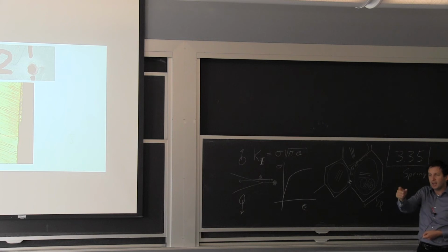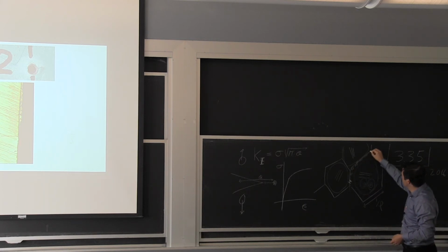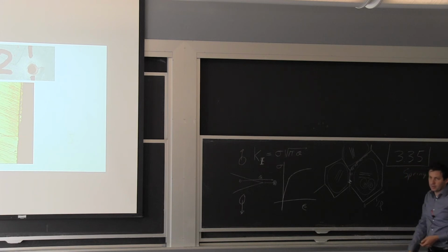and then all of a sudden you can have that very low fracture toughness because you'll just unzip through the grain boundaries. And I have plenty of images of that. It's something that's nice because you see the grains. If you want to know your grain size, you can just expose the high-strength steel to hydrogen and break it. It breaks at very low load if you have high hydrogen.